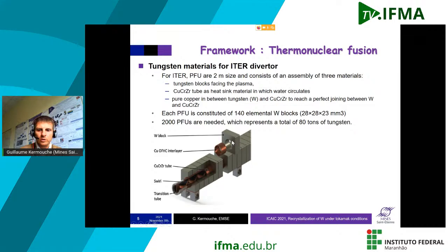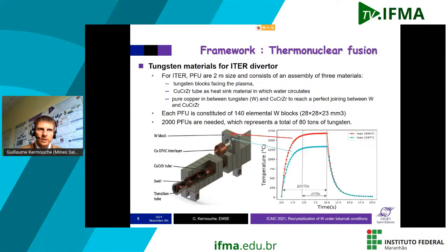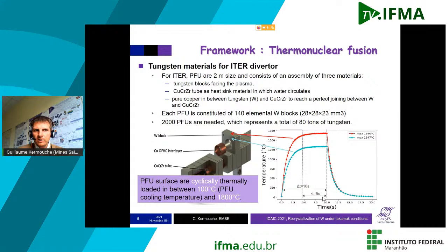So it's huge. Now, if we look at what happens to the tungsten during loading, the tungsten here will be loaded up to 2,000 degrees sometimes, and a few millimeters beneath the surface, this will be 1,000 degrees. The duration of the heat flux is about 10 seconds. So what happens is a cyclic thermal load between 100 degrees and 2,000 degrees, basically. So this is a cyclic load.